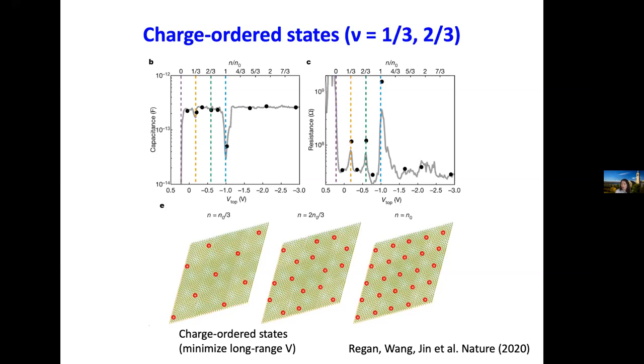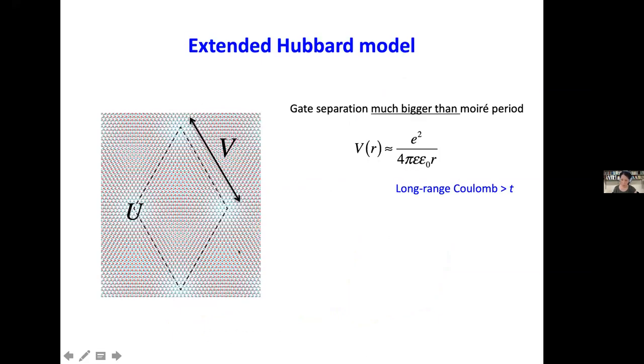So holes try to avoid not only double occupancy in one site, but also simultaneous occupancy of adjacent sites. So they like to be away from each other as much as possible. Insulating states at fractional fillings have not been observed in graphene Moire systems. So the emergence of these Wigner crystal states suggests that even the intersite, long-range Coulomb interaction is larger than the Moire miniband bandwidth. The gate separation in our devices is typically 20 to 40 nanometers away from the sample. It's bigger than the Moire period.